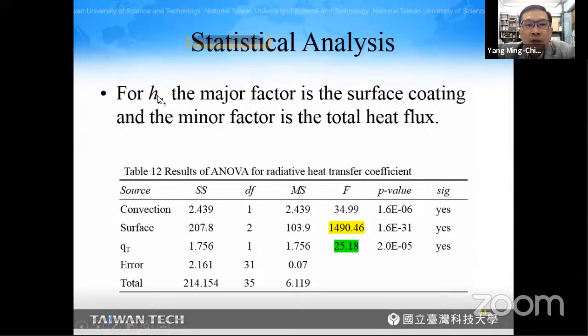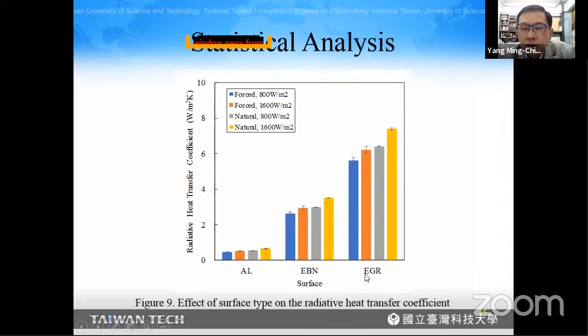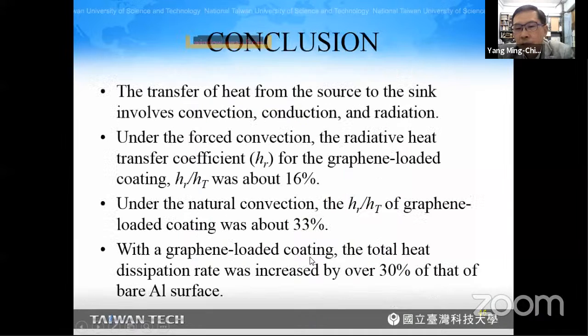And for the radiative heat transfer, the major factor is the surface coating here. And the minor factor is the total heat flux given here. This is because the coating provides another source of heat transfer, and with graphene loaded coating, the heat transfer coefficient is the most significantly improved. And this figure shows that the graphene loaded coating provides the highest radiative heat transfer coefficient. And it's much higher than bare aluminum or boron nitride loaded coating.